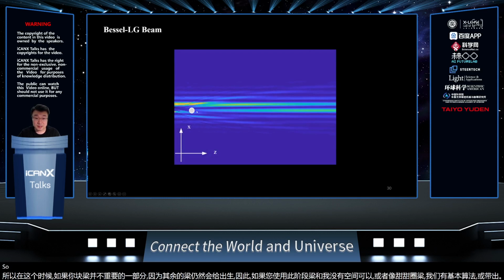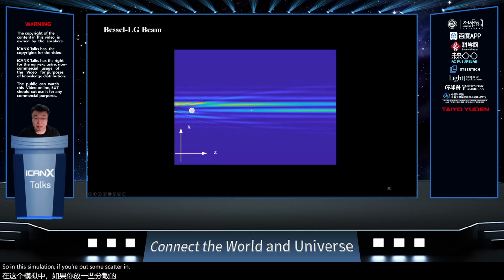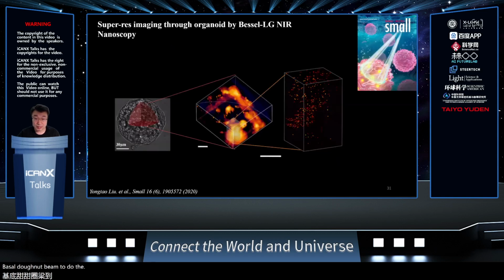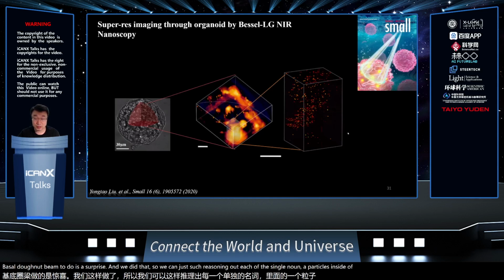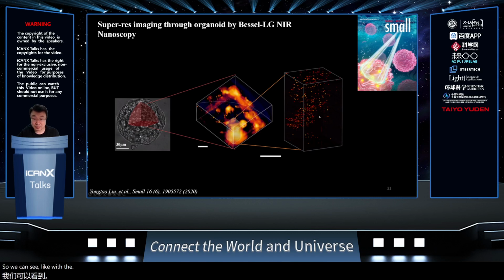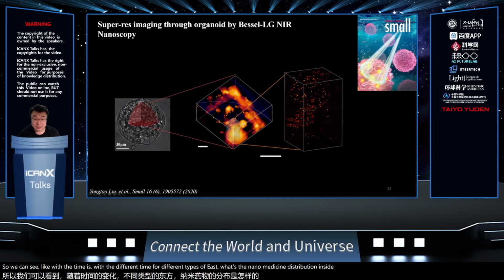In this simulation, if you put some scatterer in some position, you basically maintain good focus, still a really good donut shape. So this shows that we can use this Bessel donut beam to do the super-resolution, and we did that. We can trace out each single nanoparticle inside this organoid, and so we can see, with different times, the nanomedicine distribution inside this organoid.